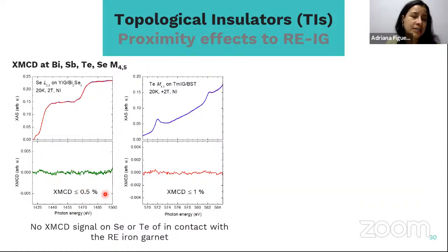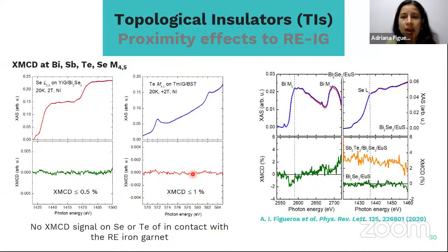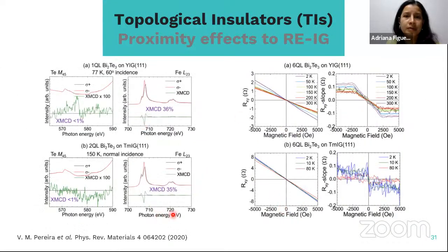And then we see that the XMCD in this case is below 0.5%. And then at the tellurium edges for the TIG interface with BST, we see that the XMCD is below 1%. So in this case, again, we have similar results to what we observed for the bismuth selenide interface with the europium sulfide. So no induced XMCD, no proximity effects in this case.